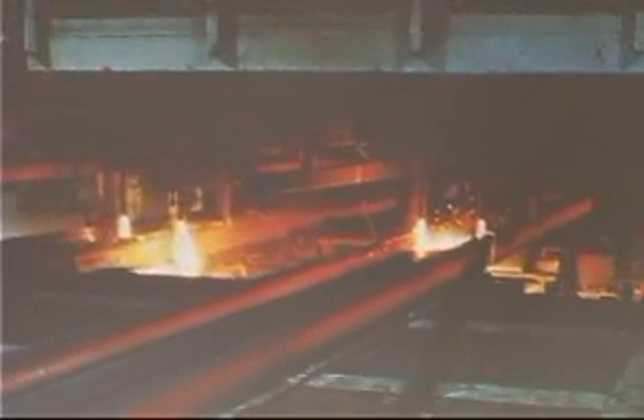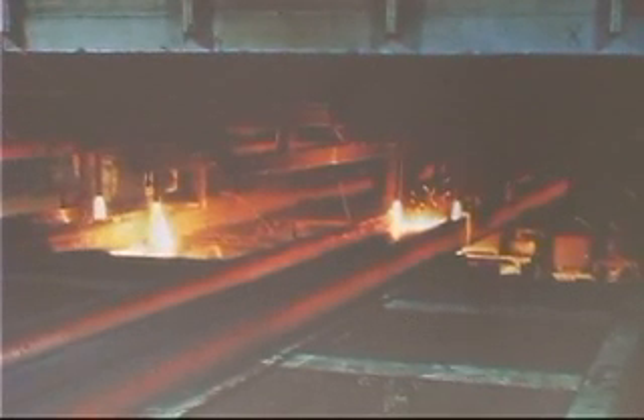And they've got oxygen lances here. You don't even need the acetylene here. You just blow pure oxygen on it because the steel's already hot, and pure oxygen just cuts right through the hot steel. Okay? So you just have an oxygen lance that cuts it off. And the lance is moving at the same rate as the strip, so you get a nice straight cut. Not really, you know, super technology.